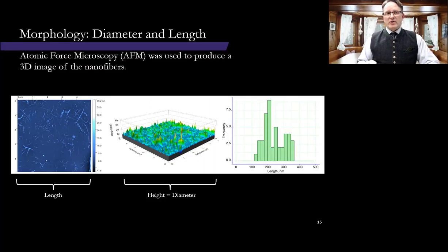Nanofibers, one point I want to make, cannot be seen by the naked eye. So in order to determine the diameter and length or the morphology of the fibers, we use a method called atomic force microscopy, and it measures the nanometer topography of samples. AFM has a resolving power that's about 1,000 times greater than an optical microscope. The way it does this is it detects the deflection in a probe as that probe moves across the surface of our sample, and then generates a three-dimensional topographic image for us.